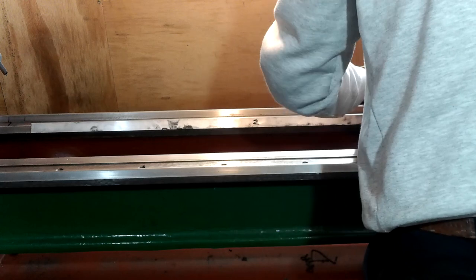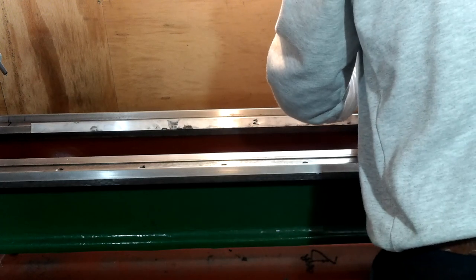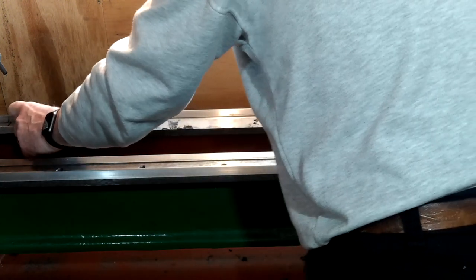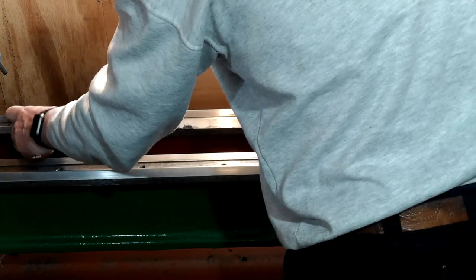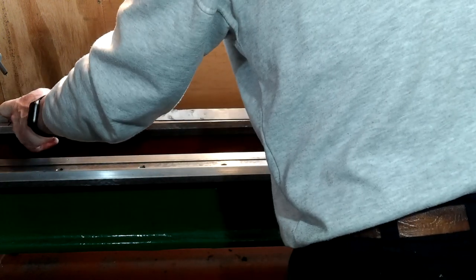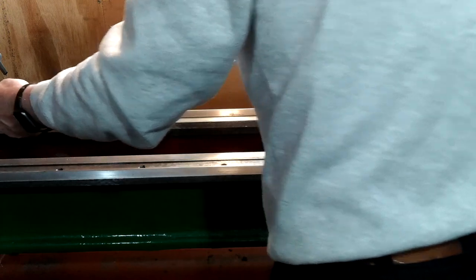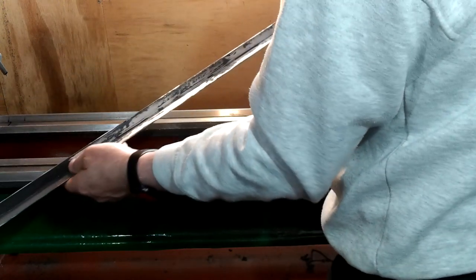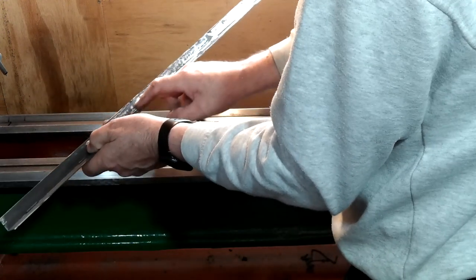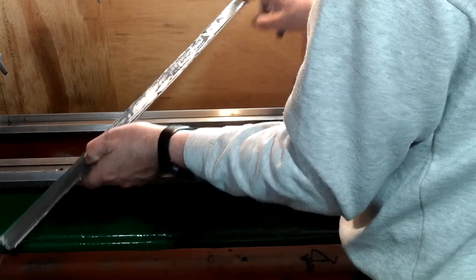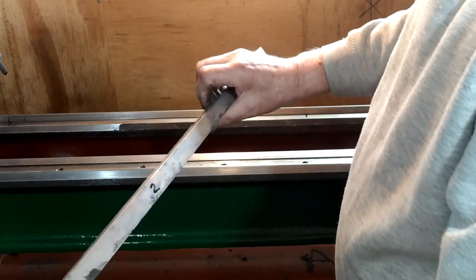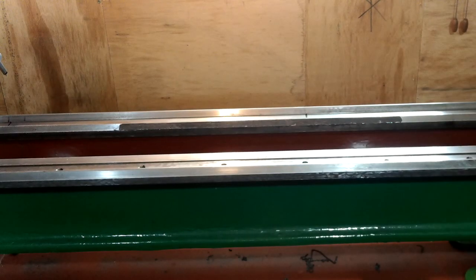About 6 hours later, nearing the end of the cure time, I couldn't wait anymore, so I removed the weights and lifted the aluminium strip. Well, it sort of popped off, really. This was the bit that I was most worried about. What would it look like? Would the resin stick to the slide or to the strip? Has the resin slumped out of the bottom? Has it even set? It seems I needn't really have worried.